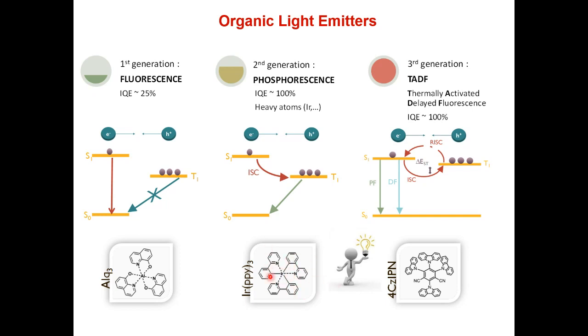But the thing is that the metallic centers cannot be used for very large applications because they are toxic and they are not really earth abundant. If you want to develop the technology, you don't want to play with metallic atoms. And so there was a third generation that we are currently developing. And the idea is to design fully organic materials without this heavy metal and with a very small energy barrier between S1 and T1, so that even though you generate T1, you can go back to S1, and then you get a very significant emission, a fluorescence signal from all the excitations. This is the new generation.